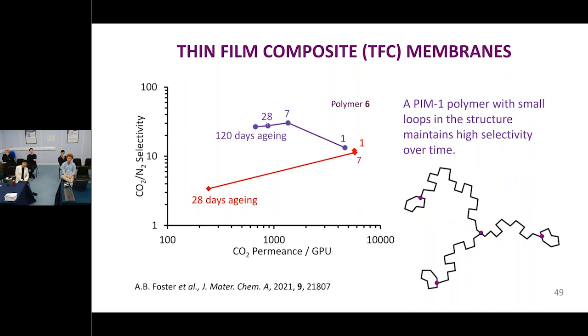But we can play with the chemistry. We came up with a sample which we believe, on average, has lots of little cyclics and a few branch points. And these perform very, very much better. Over 120 days, we lost some permeability, but we've maintained selectivity, and the aging is much, much slower. And the point here is that we can play with the polymerization. We can get different topologies. It can have a dramatic effect on what happens over time in the thin film of these polymers. And so learning how to optimize things is a key part of our current research.